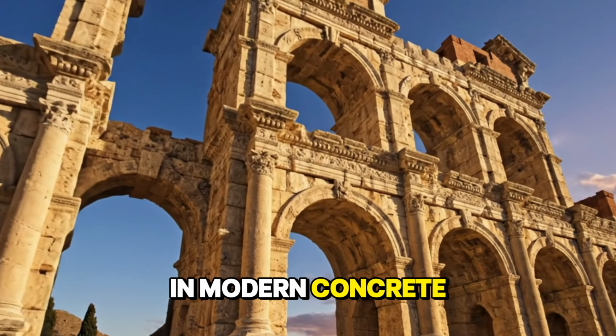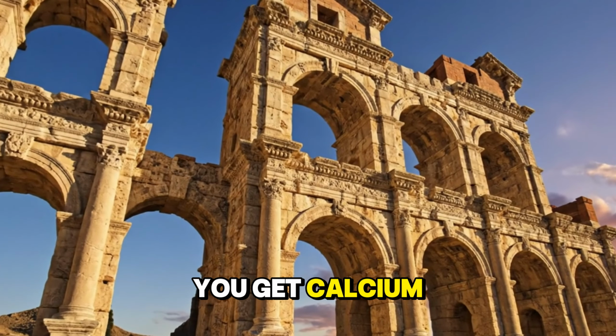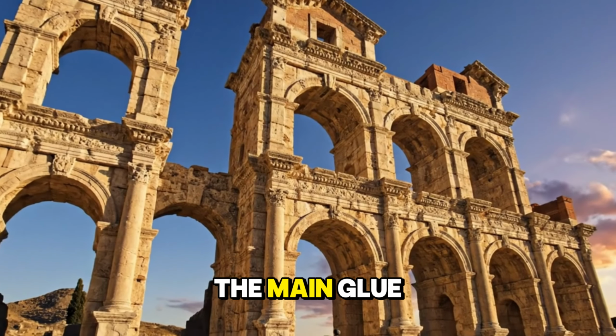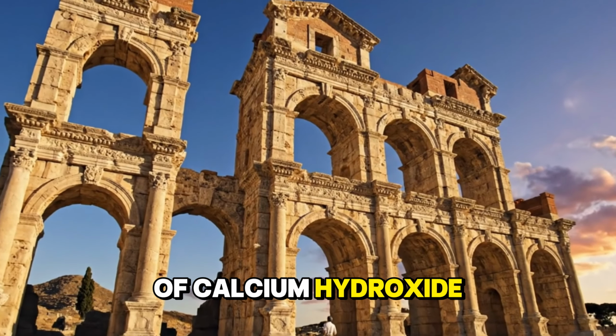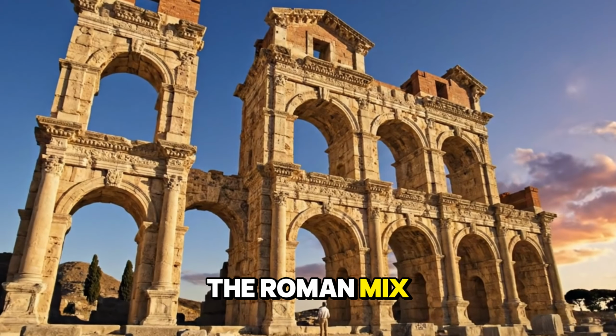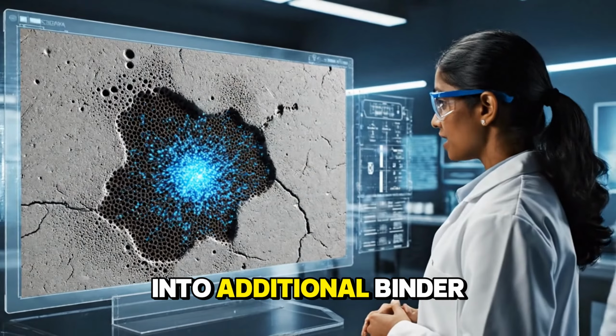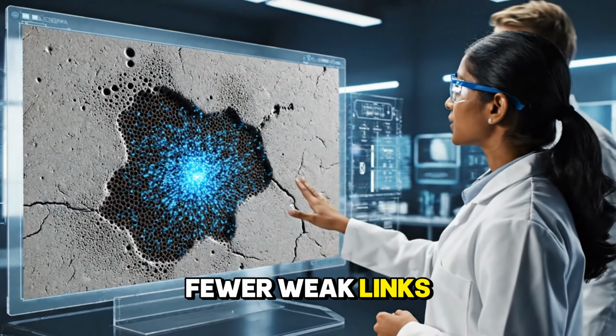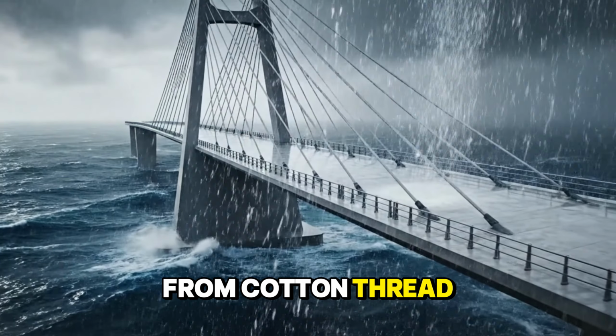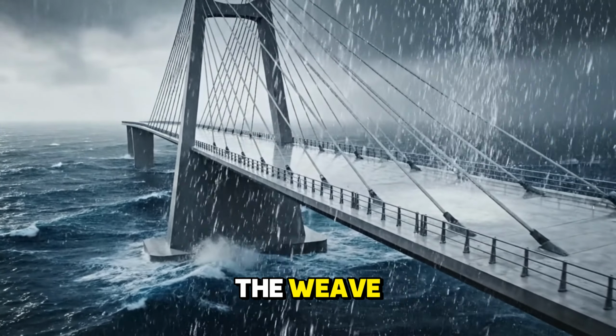In modern concrete you see a different balance. You get calcium silicate hydrate as the main glue and a lot of calcium hydroxide that can leach out. The Roman mix consumes most of that free lime into additional binder. Fewer weak links, fewer leachable products, tighter pores. It is like upgrading the stitching on a jacket from cotton thread to Kevlar, while also shrinking the weave.